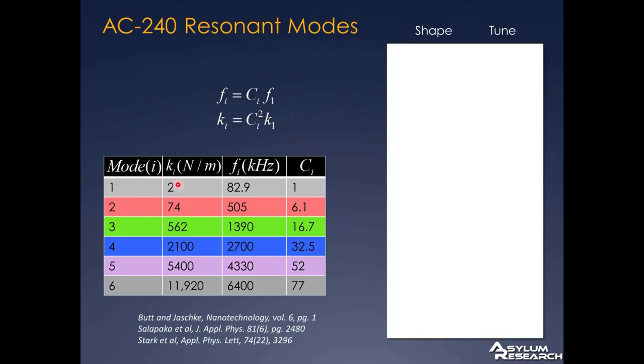For an AC240, the spring constant of that first mode is about 2 newtons per meter. The one I'm working with here has a resonant frequency of about 82 kilohertz. The next modes up have frequencies given by this expression here, for i equals 2, 3, 4: the first frequency times this constant C. The dynamic spring constant, the stiffness of that mode, goes like this number C squared.